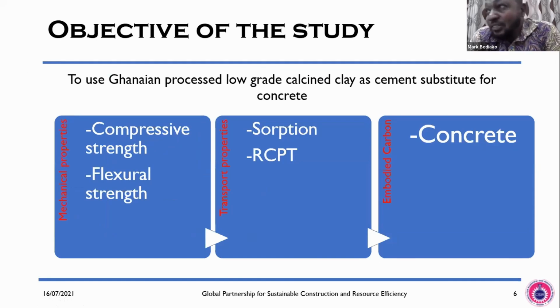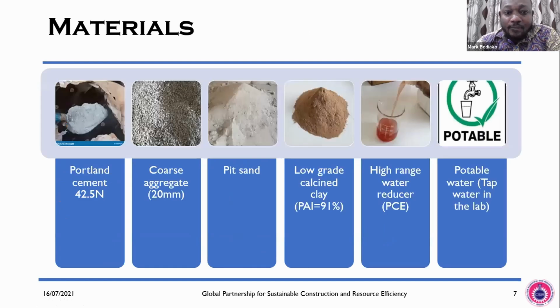Well, so the objective of this study is to look at processed Ghanaian low-grade calcined clay as a cement substitute for concrete. And then to achieve this, I have to look at the mechanical properties, which include the compressive and the flexural, and then the transport properties, looking at the sorption and the rapid chloride permeability test, and the embodied carbon of the concrete of the various formulated mixes. So these are the materials that were used, the Portland cement in a grade of 42.5.